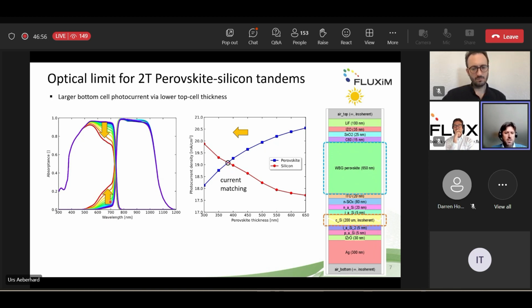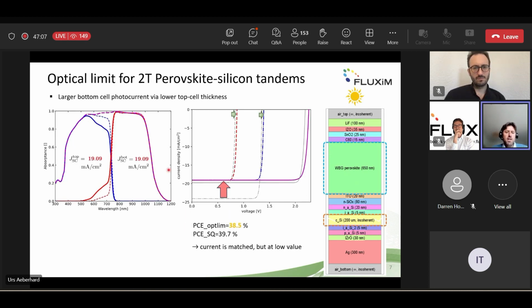So you can see how here in this overlap region, the contribution of the bottom cell increases while the top cell contribution decreases. If we do that, we find a matched situation. However, the current is still quite low, so we increased the efficiency a little, but it's still not ideal.